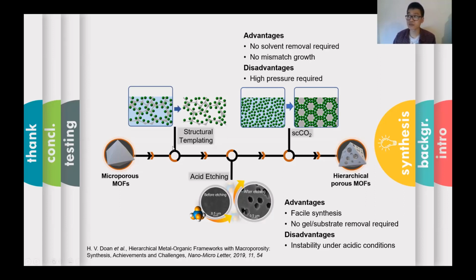The method that I'm going to introduce today is the use of supercritical CO2, where the MOF precursor solution was pressurized with CO2 in a critical condition, like 40 degrees C and above 71 bar. And this method has been claimed to have many advantages for the synthesis of hierarchical MOFs.